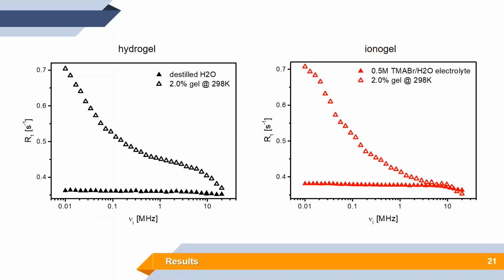And on this slide, I present two nuclear magnetic resonance dispersion profiles. The black one is for our reference system, which is the hydrogel system, and the red one is for the Ionogel. You can see that the shape of the NMRD profiles in the gel phase is similar, and the relaxation rate is also similar. So to interpret and analyze this data, let's first start from the hydrogel system, which is the less complicated system.